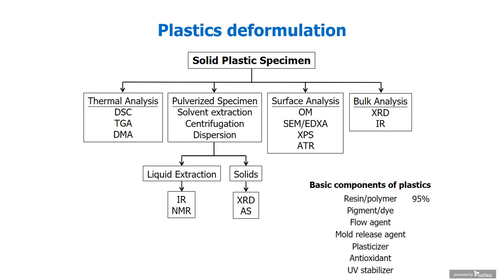Now, if you have a sample that you can pulverize and therefore separate perhaps soluble fractions, you can use solvent extraction, such as a very effective Soxhlet extraction, centrifugation, dispersion, and then filtration. The solid can be separated from the liquid and separately analyzed by X-ray, elemental analysis, or in the case of soluble components as well, you can use NMR, IR, and other spectroscopic methods. Now, if you have a surface before destructive separation, one can employ XPS, ATR, SEM microscopy, and looking at the bulk analysis, one can employ X-ray scattering diffraction methods.